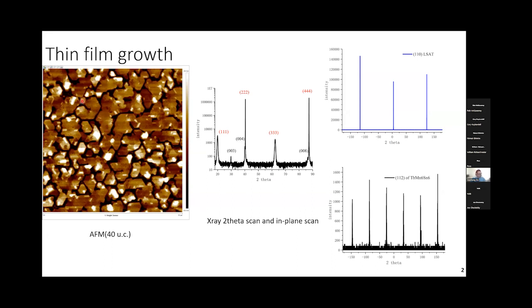And it actually is an island structure film. So the islands will form the connecting current path, which makes the film conducting. The middle panel is the X-ray 2-theta scan. I used the red labels to label the peaks from the substrate. We use the LSAT 111 substrate, so we can see only the peaks from the 111 direction. And the black labels are the film peaks, so we can see the film is C-axis oriented.